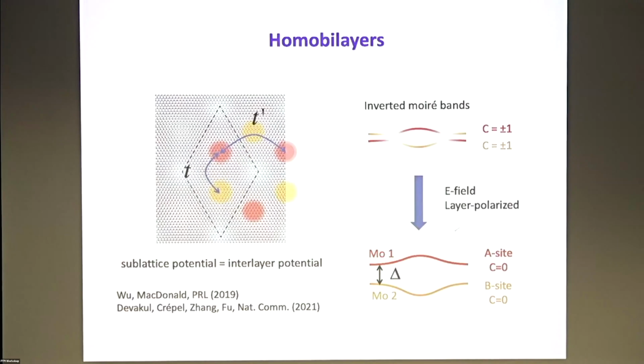Okay. And one thing I also want to mention is that for the sublattice sites here, the wave function is actually living in two different layers in a sense. So when you apply a vertical electric field through the bilayer, the Stark shift is the same as the interlayer potential difference. Well, the interlayer potential difference is the same as the sublattice potential difference in this case. So if you can apply an electric field to the system, you can also change the bands from Chern bands to topologically trivial with a Chern number equal to 0. So by tuning the electric field, you can also change the band structure of the system.